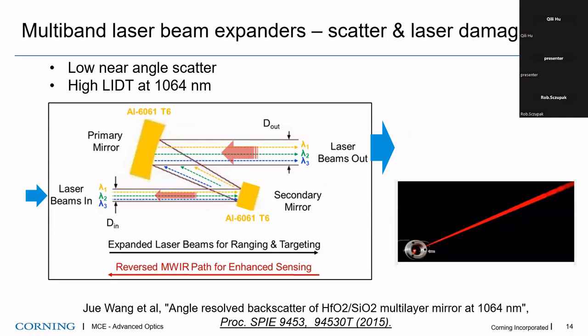And now we step into laser damage at 1064. We have been making this product for many years, more than 10 years. Over the years, through optical engineering, we try to gain a better understanding. Basically, this is just a two mirror system that expands multiple wavelengths, and it also has the capability to enhance the signal to noise ratio in sensing in the mid-wave IR. There are a couple of requirements. Here I just highlight low near angle scattering, because of the beam path length to the long distance target. And another is laser-induced damage at 1064.